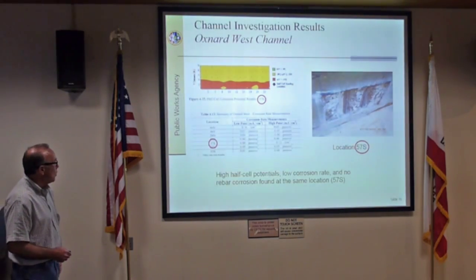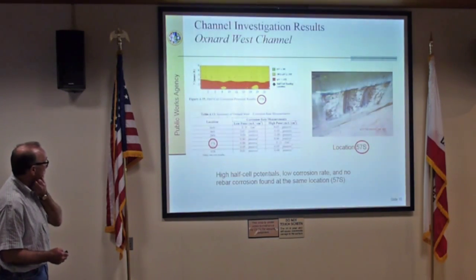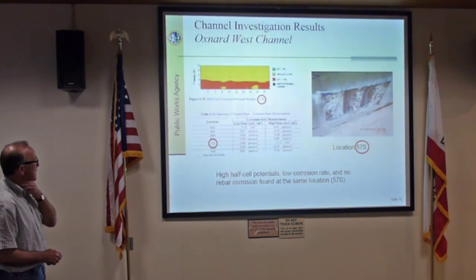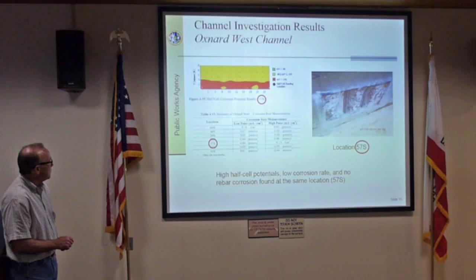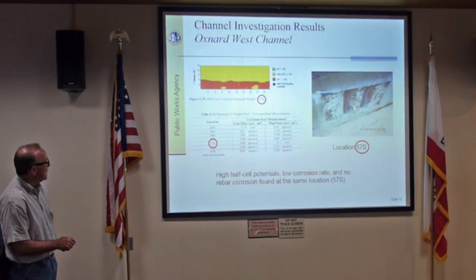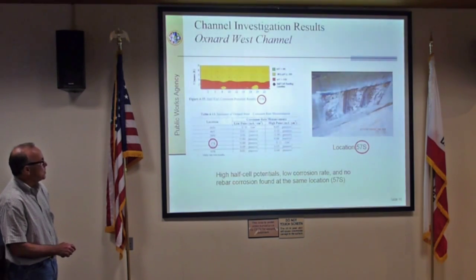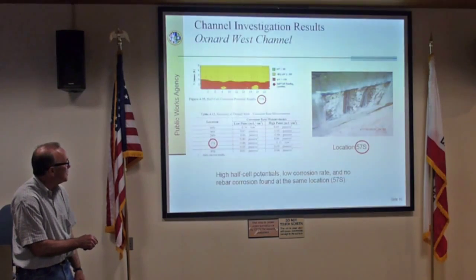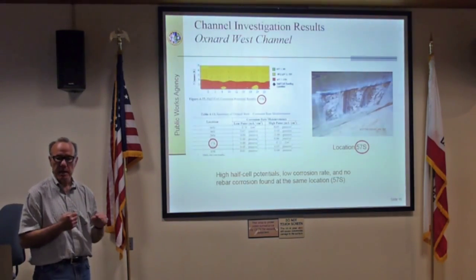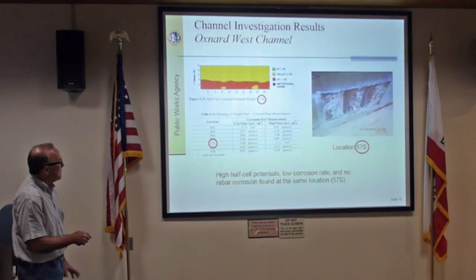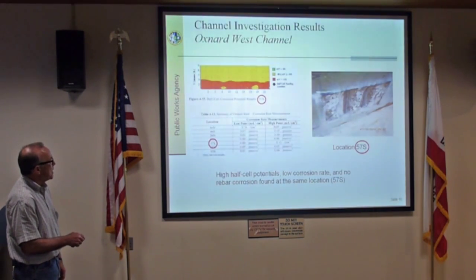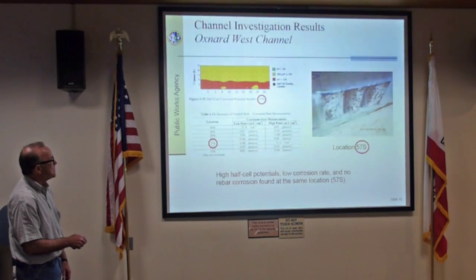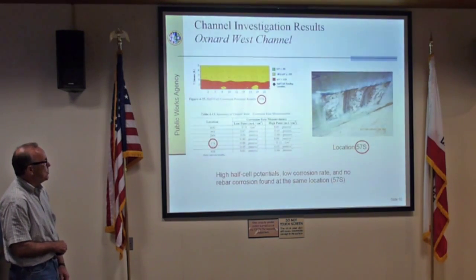So we take a wall panel here. This is one of the panels, Oxnard West channel. These are the half-cell potentials, and we're going along for this station 50, our panel 57S. You go from one side to the other side. Wherever it's red is an indication where the corrosion half-cell potential, when it's more negative than -350, tells us there's a 90% chance there's active corrosion. When it's between about -100 and -350, there's not much chance, and where it's more positive than -100, there's no activity at all.